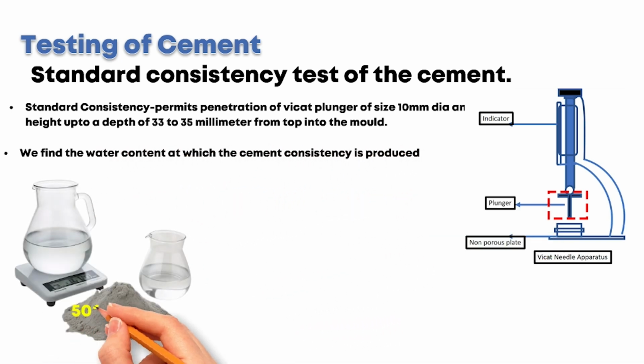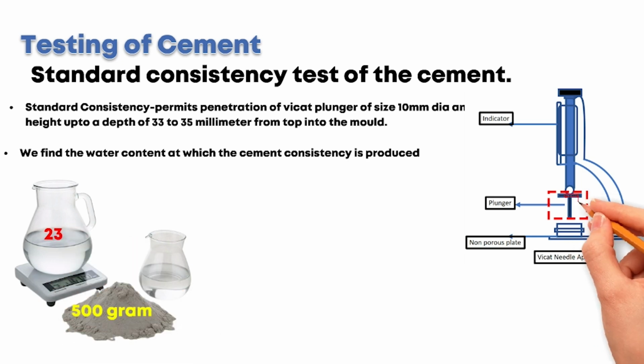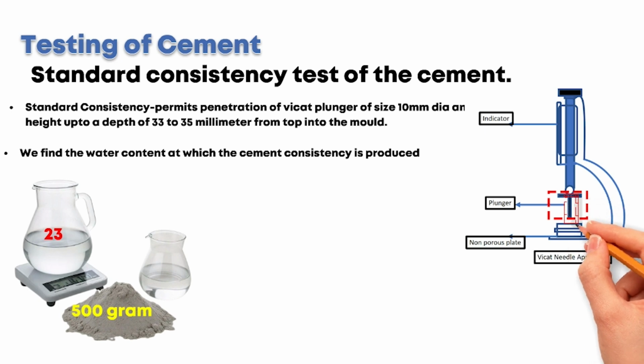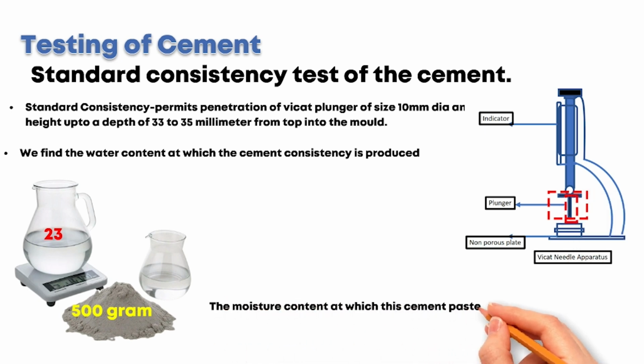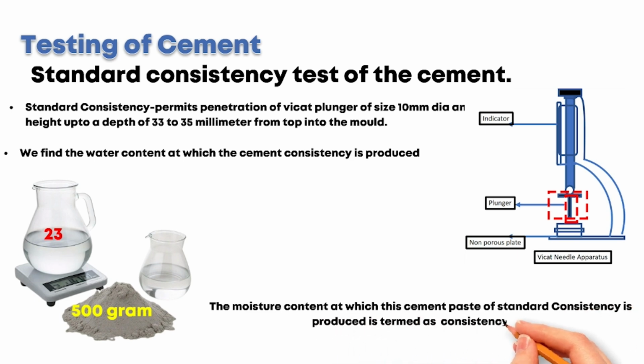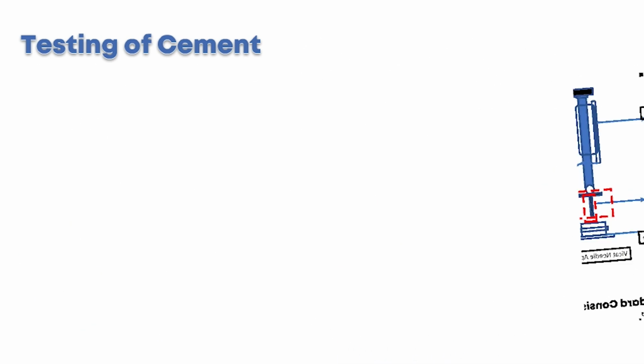Take 500 g of cement and add 23% of water by weight of cement in the first trial. Lower the plunger gently up to the surface of the mold and release quickly. The moisture content at which this cement paste of standard consistency is produced is termed as consistency P.